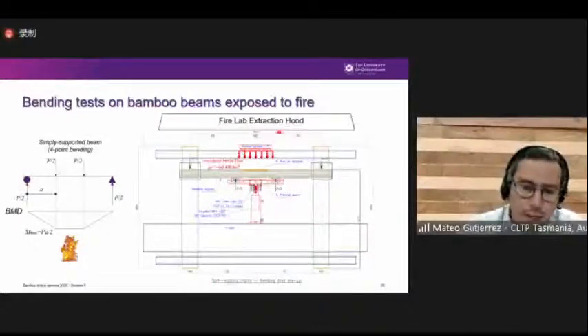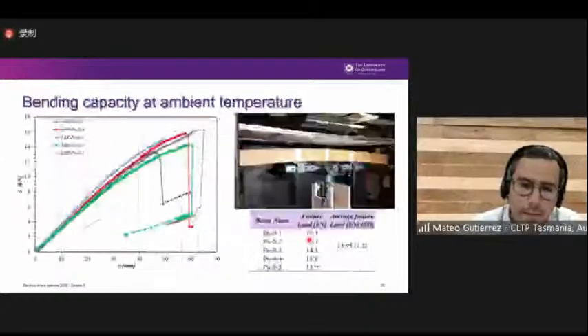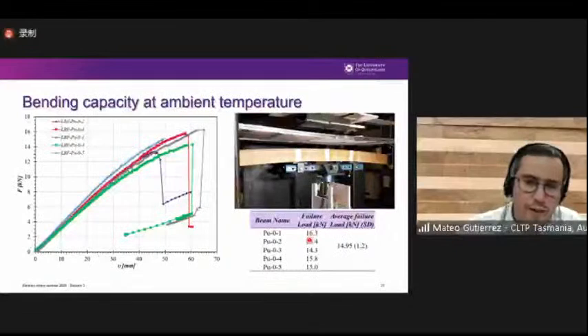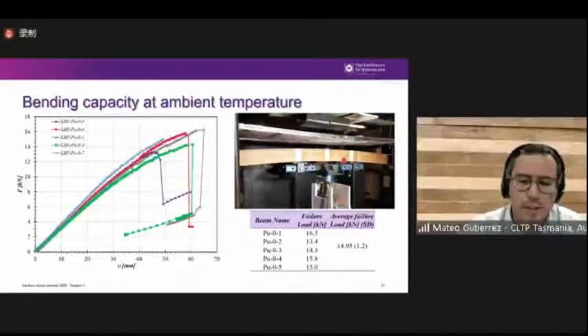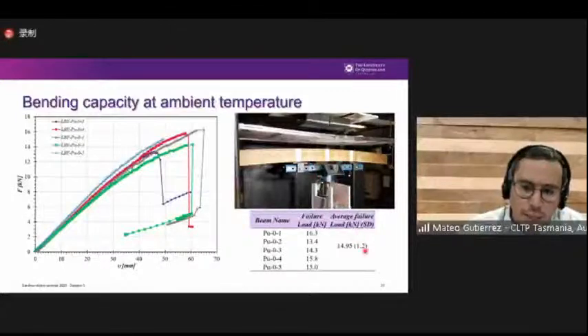And then we apply the heat, a constant incident heat flux with a radiant panel. But before doing any fire test, we conducted some tests at ambient temperature to determine the capacity of our beams at ambient temperature. So basically we found that for these beams of this size, the failure load was around 15 kilonewtons.